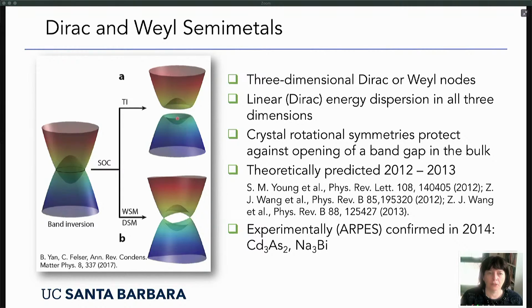So we have still this inverted structure, but we have a gap opening here. And this is what results in a three-dimensional topological insulator. But in certain materials, and these are the Dirac and Weyl semimetals, there are certain crystalline symmetries that prevent a band gap from opening at certain points in the Brillouin zone. Around these touching points, the Dirac nodes or Weyl nodes, you have a linear energy dispersion, and you have this linear energy dispersion in all three dimensions.